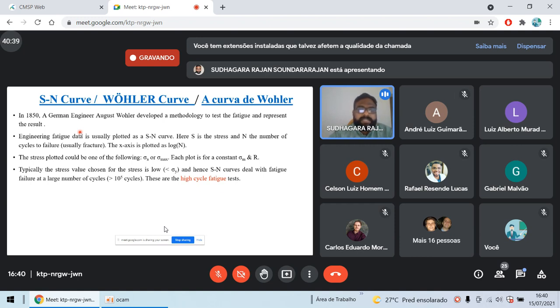Okay, typically the stress value chosen for this test is lower than sigma y, obviously, because if we go beyond sigma y, we will initiate plastic deformation in a gross way. As a whole, you will initiate the plastic deformation. So there's no sense in doing the fatigue testing. Okay, so that means high cycle fatigue testing. So always we will start with a stress level which is lower than the yield strength, and hence the SN curve deals with fatigue failure at a larger number of cycles.